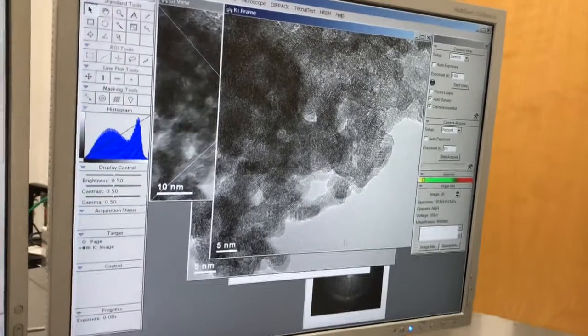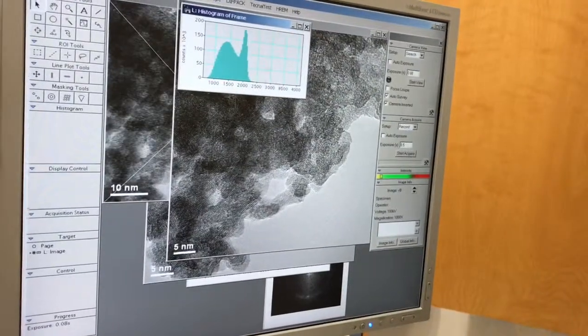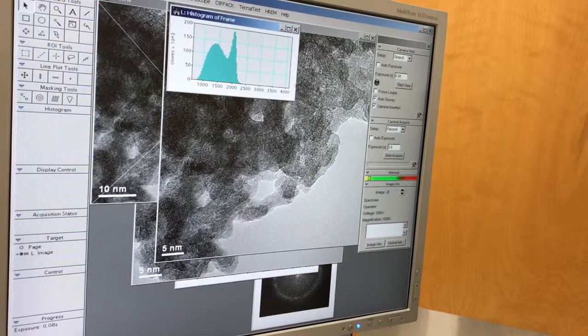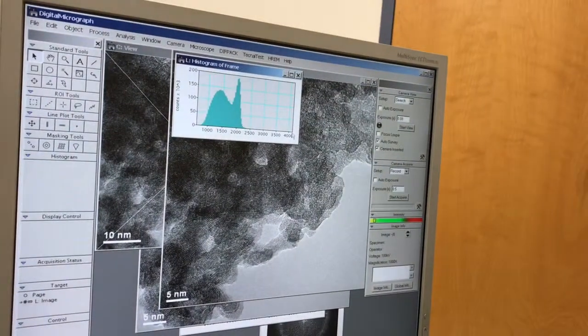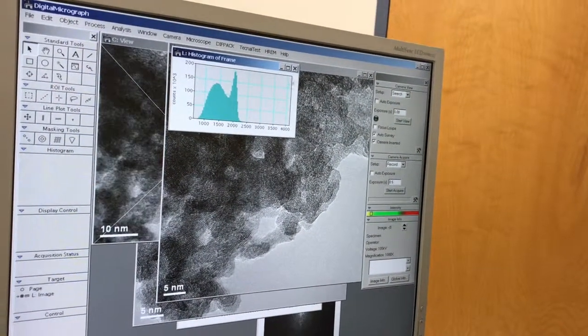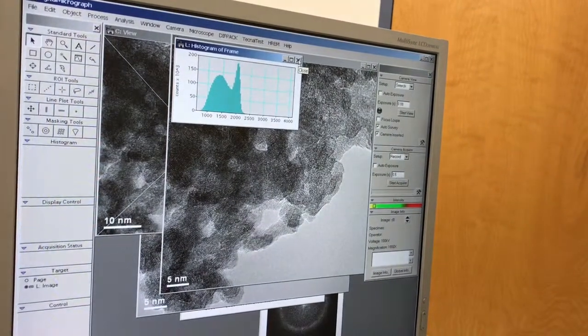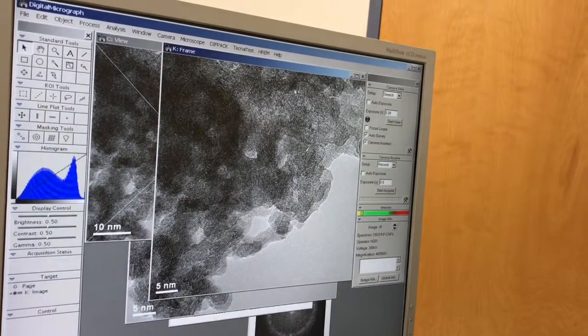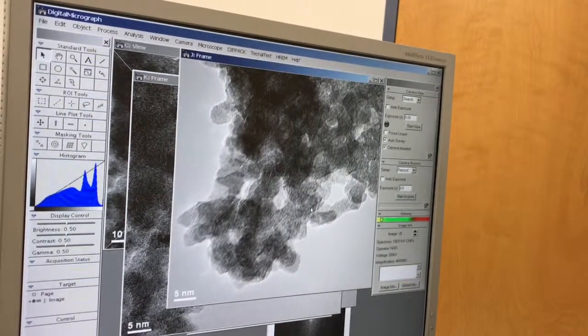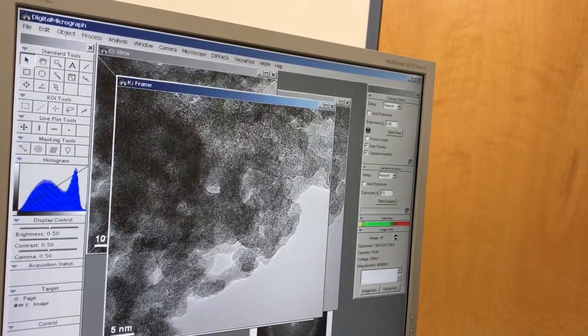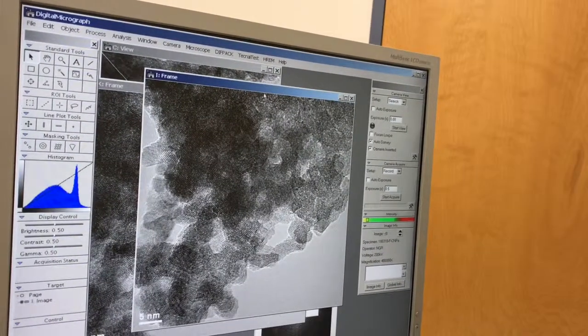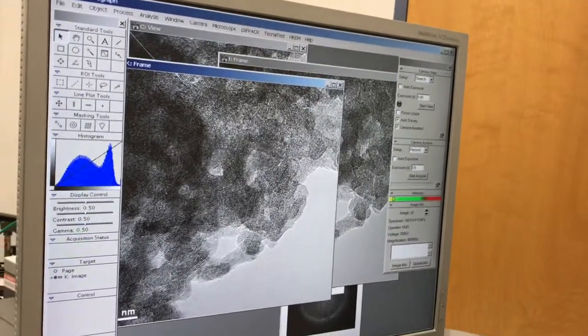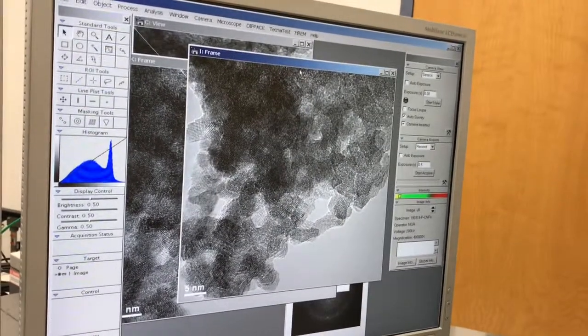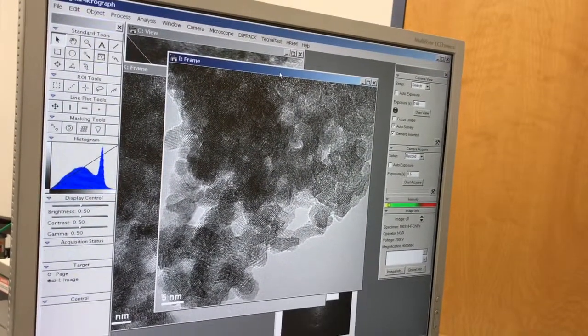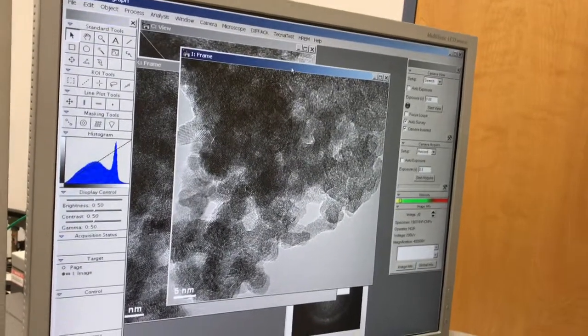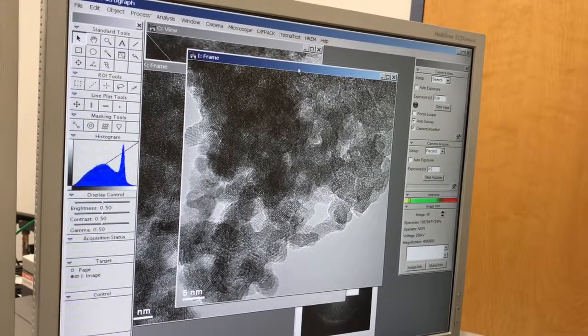Okay, so that's half a second. Again, looking at the histogram, I've lost a lot of dynamic range here. I'm only going to around 4,000 counts, but this is still a way more useful image than this. If we look at this, that's 1 second, that's half a second. The 1 second image is a lot better. So I did get a benefit by doing that, but again, I didn't exceed the time scale over which I start to see instability in the picture.